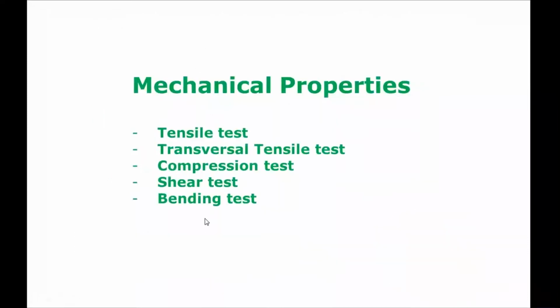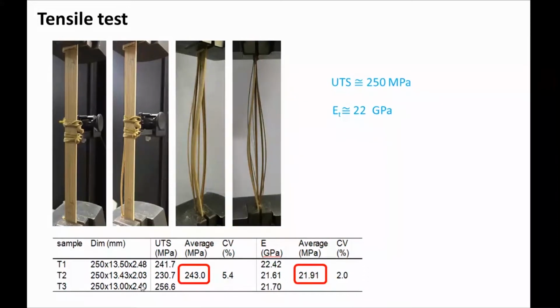About the mechanical properties, we should talk about the tensile test, transversal tensile test, compression test, shear test, and bending test. In the tensile test that we did in the laboratory, we realized that the ultimate tensile strength on average for bamboo is approximately 250 megapascals. The exact values are for T1, T2, T3 in this dimension, and it's the CV, and the average for E is about 22 gigapascal. You can see the average and the CV of this test. It's a very low CV. It's very acceptable. That means that the test is very acceptable.